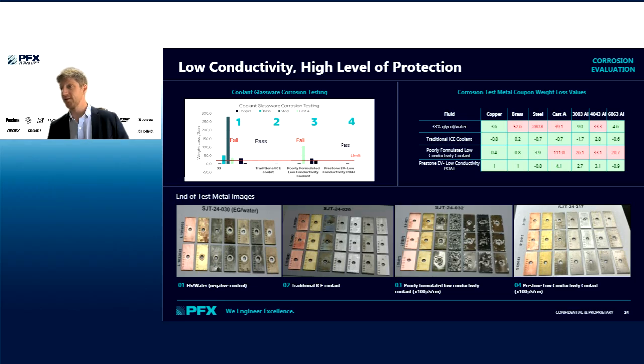So then we look at a poorly formulated low electrical conductivity fluid, and this is number 3 here. And we can see just from the visual of the poorly formulated low conductivity end of test specimen that these specimen have been terribly eaten away and corroded by the fluid in there. And so this fluid is actually a fluid that was commercialized as a low conductivity EV fluid prior to the GB specification being released. This fluid was later recalled due to corrosion issues within the system.